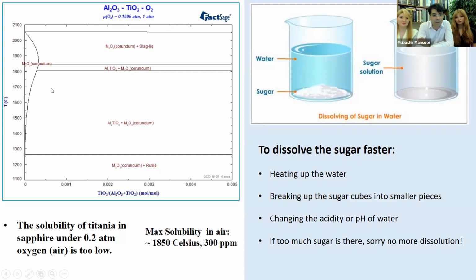So let's look at the diagram on the left. If we actually look at the solubility, so over here, this hump that we see here actually shows how much solubility we can have of the rutile in sapphire. And it turns out that the maximum solubility, when you're heating it in air, happens at about 1850 Celsius, which is a very high temperature. Why is this a very high temperature? The best furnaces cannot usually exceed 1700 Celsius commercially. So that's the problem. And also another problem is the maximum concentration of rutile that can be dissolved in air is actually very limited. It's quite a small amount.